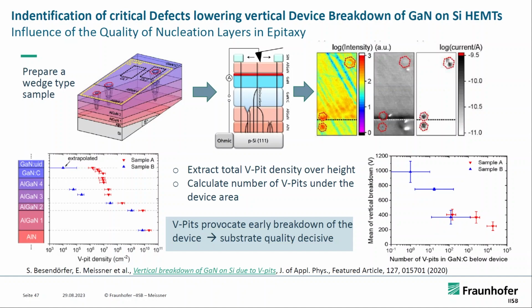And now you count the number of V-pits underneath a structure, and you see that the red ones and the blue ones, sample A and B, have different counts. And the number of the V-pits you can associate to the mean of the vertical breakdown voltage.